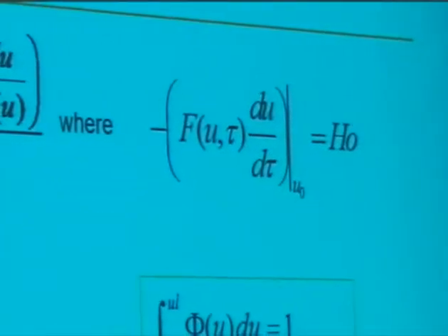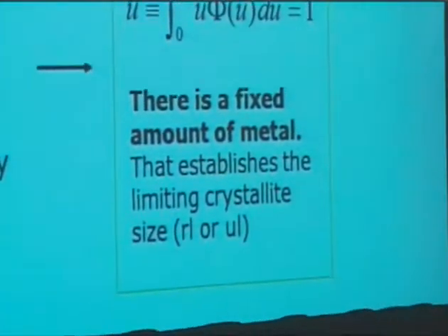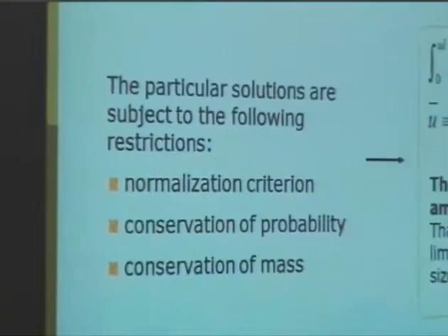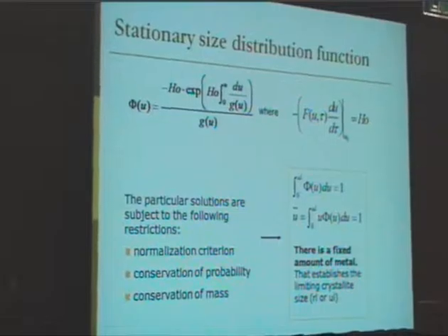The idea is very simple. Really, this is a particle size distribution, and this is a non-dimensional problem. Everything is non-dimensionalized. And the trick that we had to use to solve the problem is to realize that there were different criteria that were not being satisfied previously: the normalization, conservation of probability, and conservation of mass. So the problem is a simultaneous problem. And we also found that you had to integrate just on part of the domain, and that made the problem simpler.